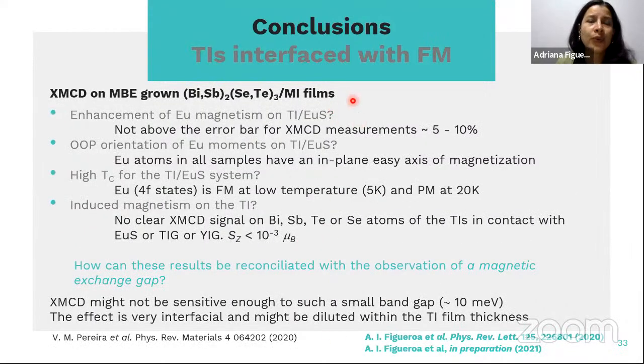And then I also showed you some results of XMCD on these TIs interfaced with magnetic insulators. The two kinds of insulators that I used were europium sulfide and yttrium iron garnet. And I showed you that there was no clear XMCD signal on the non-magnetic atoms of the TIs in contact with the magnetic insulators. And this is in stark contrast to what has been reported from transport measurements and other characterization techniques for such heterostructures. And there are still some open questions, because we need to know how to reconcile this observation with the observation of a magnetic exchange gap.